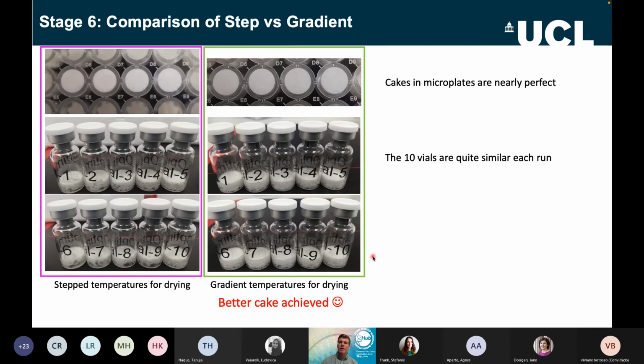Should just point out though that all of our work was at a fairly shallow fill in microtiter plates, and the cakes in there were perfect, or nearly perfect, whereas it's going into the vials where we start to see the differences. There seems to be a really near perfect layer in the top half of the vial, and the bumping tends to concentrate at the bottom of the vial.